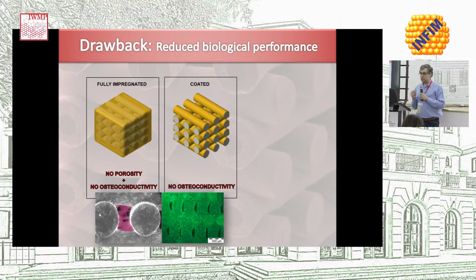But even in coated structures, or even in fully impregnated structures where the porosity is created in situ, you will still have the polymer on the struts. And this will isolate the good bioactive properties of these ceramic materials, of calcium phosphates or bioglasses. The cells will not know, because it's already covered with a polymer. So that's a problem. You are losing bioactivity. You have no osteoconductivity, no porosity in the case of fully impregnated. So how do we solve that?